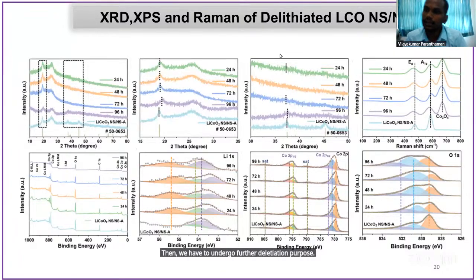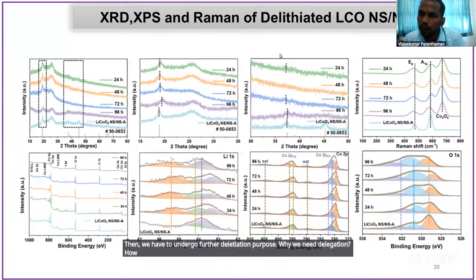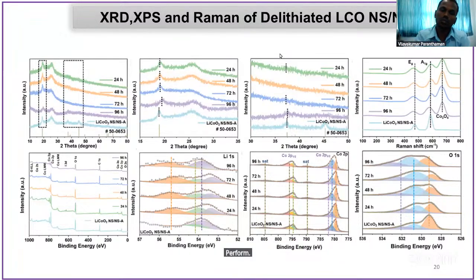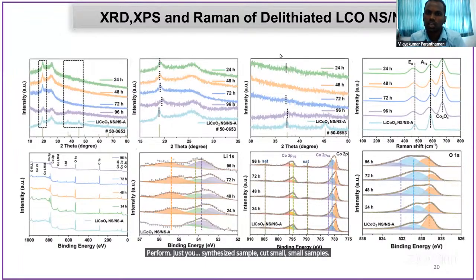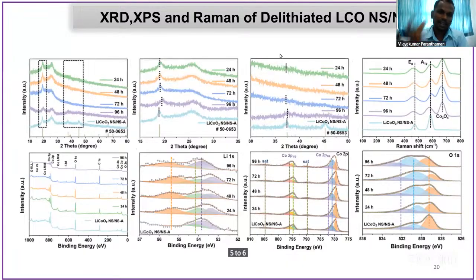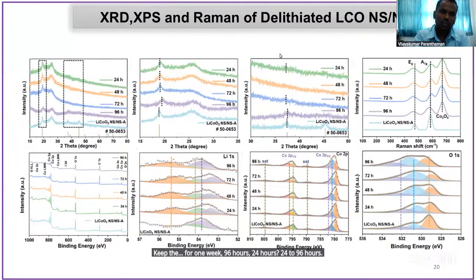Why do we need delithiation? How is the delithiation performed? Just take your synthesized sample and cut small samples, like 1 cross 1 or 0.5 cross 0.5 centimeter square. You can cut 5 to 6 carbon cloth pieces. Then immerse them in the iodine solution. Keep them for 24 to 96 hours, up to 1 week. Then after the 24 hours, take the sample and do the XRD and the XPS analysis.